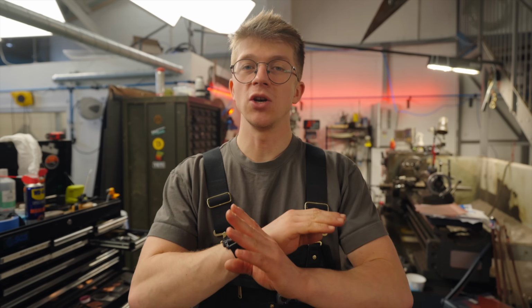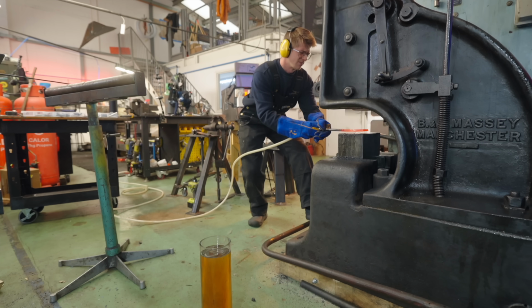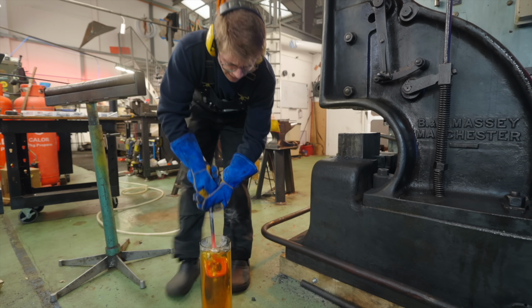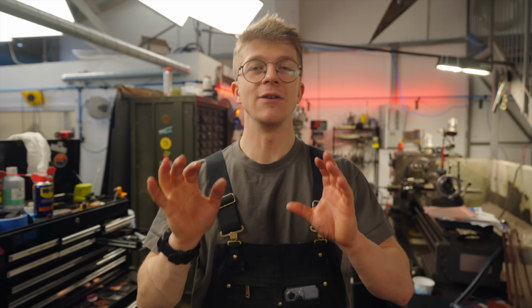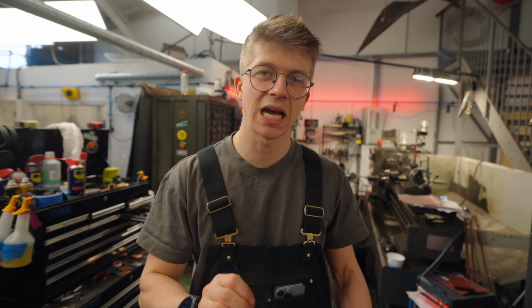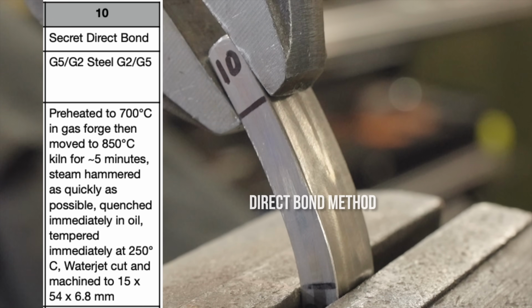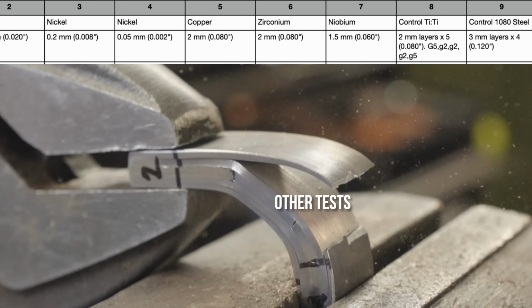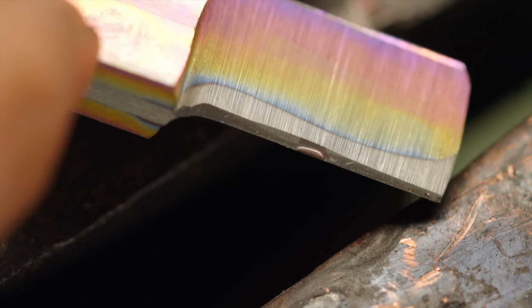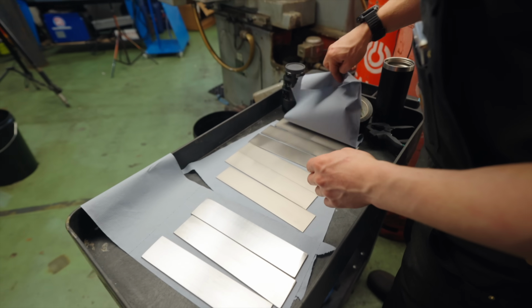And that is using no interlayer, heating the material, forging it together, bonding it, and then immediately quenching it, leaving as little time at temperature as possible in order to reduce the amount of that intermetallic compound formed. And that works better than any other technique that we tried. There was one downside though, which is that we weren't able to get the steel core hard enough, and so this time around, we have no interlayers.